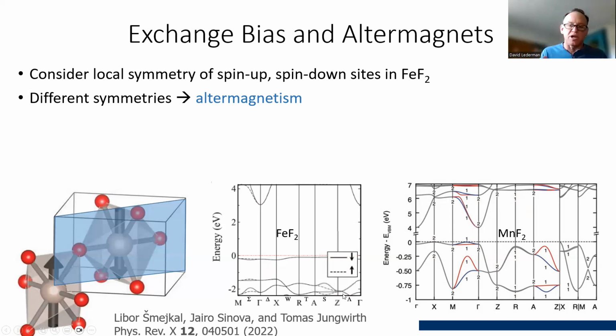And in fact, if you average everywhere, there is no net polarized spin current. Like in a ferromagnet, of course, you have that in all directions, but in an antiferromagnet, you only have it along certain directions, and they've made certain predictions about the transport, and people are very interested in studying this material. There's actually a conducting, metallic antiferromagnet, ruthenium dioxide, which has also this same rutile crystal structure, and there's a lot of interest in this right now.